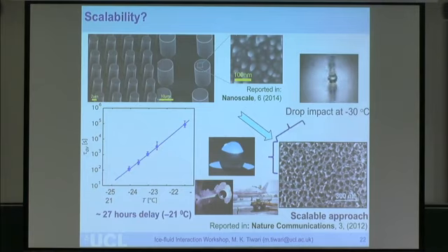You have an electrochemical bath, and you can create surface nanotexture in plate sizes that fit your bath really. So you are just limited by the size of your bath. Of course, everything has to be controlled in terms of temperature and so on. It's used quite widely in the industry. So the thought is, and this is an example of what we have achieved so far. This is a very hydrophobic surface as well, which we reported. And the next step after that is to go towards even finer precision in surface texture.